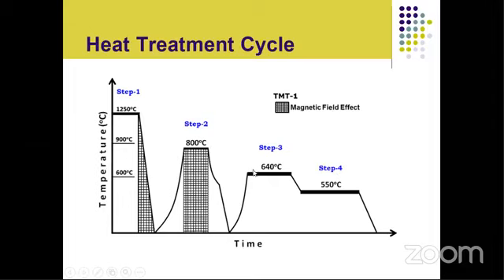After that, we give two heat treatment cycles, which are called step aging. First step was solution treatment. Second step is TMT. TMT stands for thermomagnetic treatment. And the third and fourth steps, these are actually step aging. We heat treat this material under argon atmosphere at 640 degrees Celsius for 3 to 4 hours. And then again, this material is heated at 550 degrees Celsius almost for 24 hours. These temperatures can be tailored or changed according to your composition.